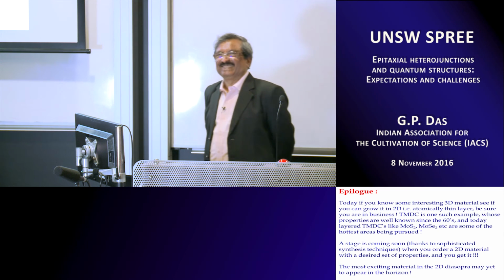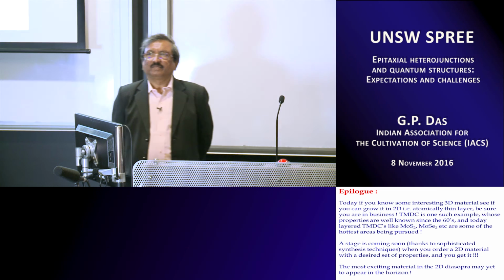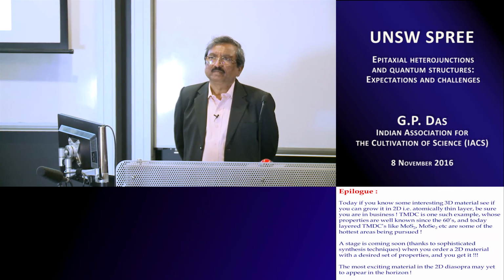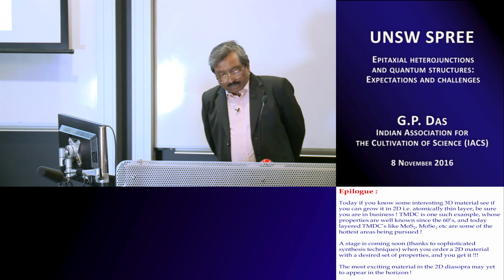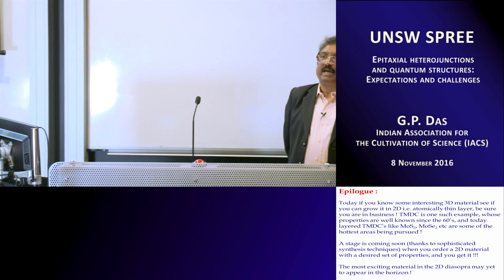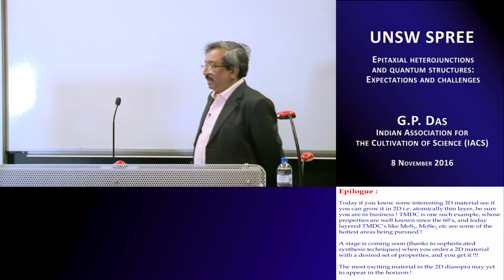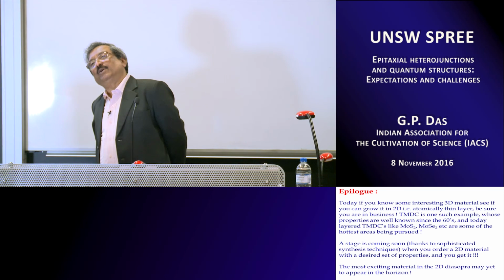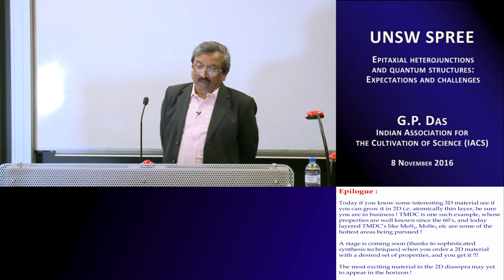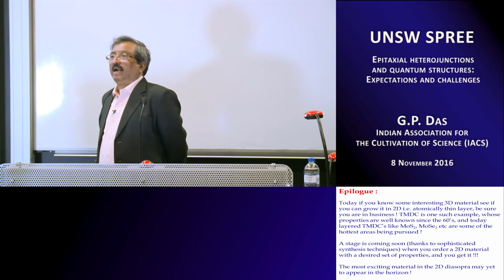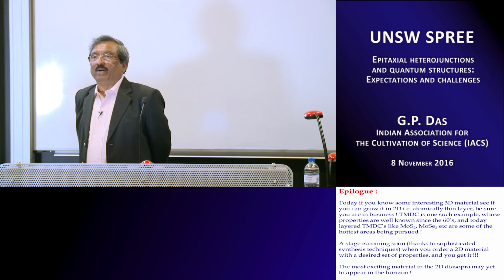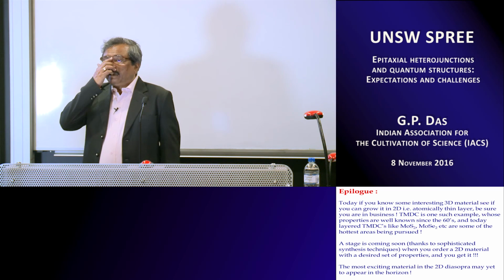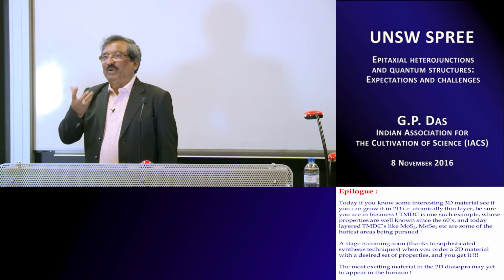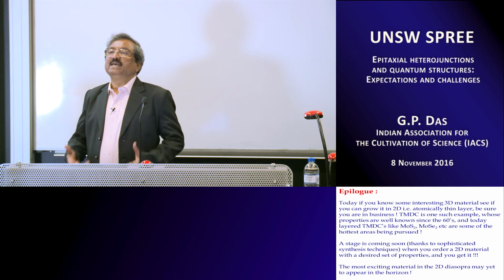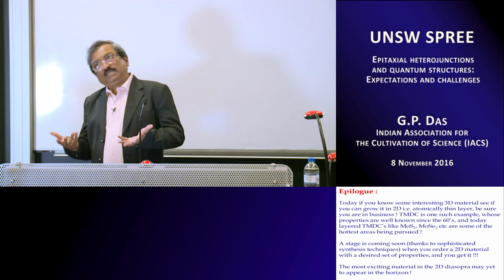Thank you, Professor. May I ask, have you ever applied synthesis of nickel-111 in experimental synthesized situation? Or is it all theoretical by the DFT? Oh, there are attempts to grow many of the materials, graphene, hexagonal boron nitride. They have actually been grown already on nickel-111, and particularly nickel-111 and copper-111 are the most used because there is a very good lattice matching between the nickel-111 and the graphene and hexagonal boron nitride, and that is why these are the most popular substrates. So these have been already done.